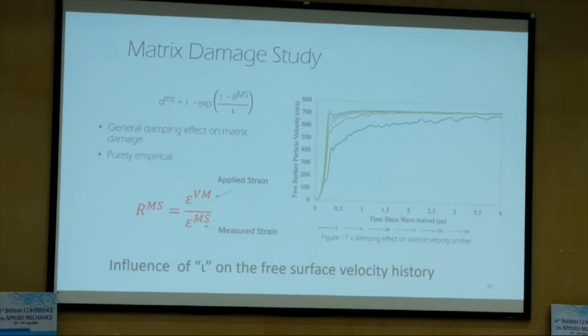Okay, let's go to the next one. Now, this is matrix cracking under shear. Look at that. The growth parameter, iota, you change it, and look at the way it changes. Now, that's a Hugoniot elastic limit, right? And you can see that it significantly affects the profile. That tells you that matrix cracking is changing the profile.